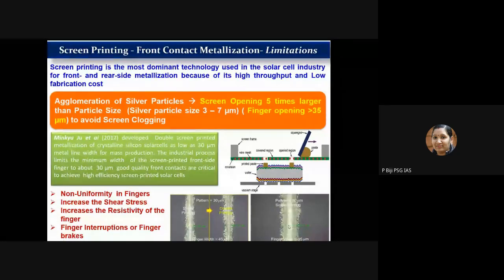Another disadvantage is non-uniformity in the fingers. If the printed lines are non-uniform, that will increase the shear stress, and that will increase the resistivity of the finger. As you reduce the finger width, the possibility of finger interruptions or finger breaks will be enormous. That is another challenge which has to be thought about. Such non-uniform fingers will also increase the series resistance. So these are some of the disadvantages of screen printing of silver paste.